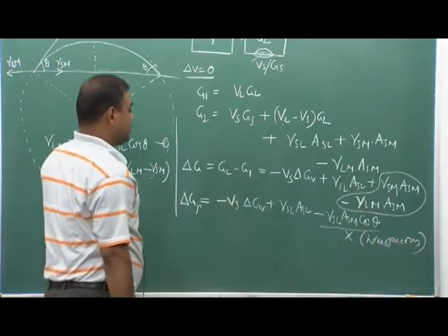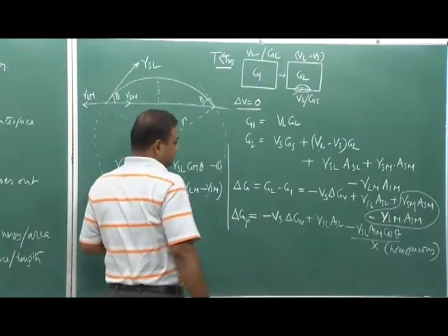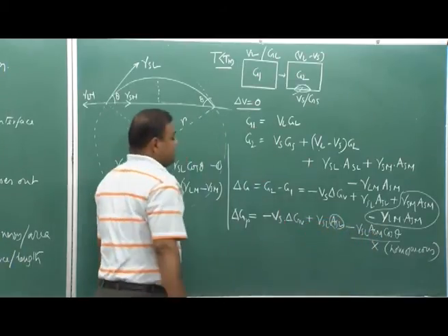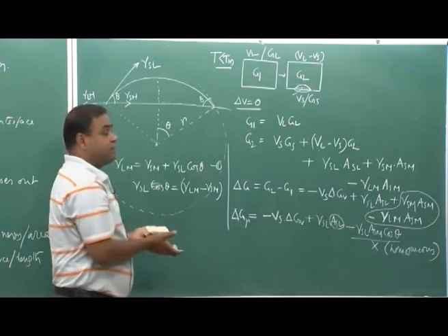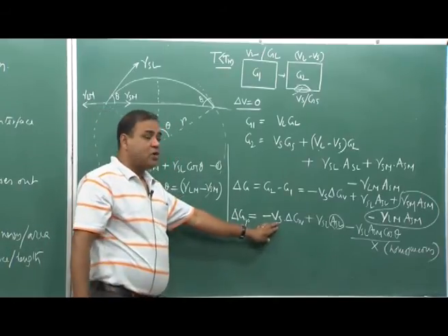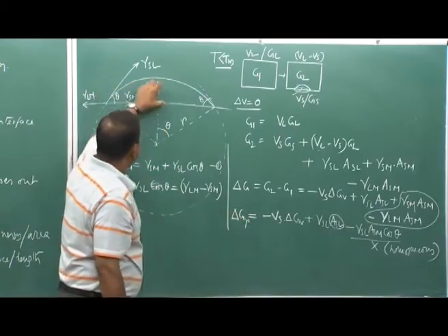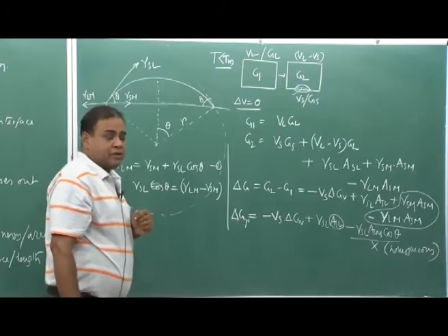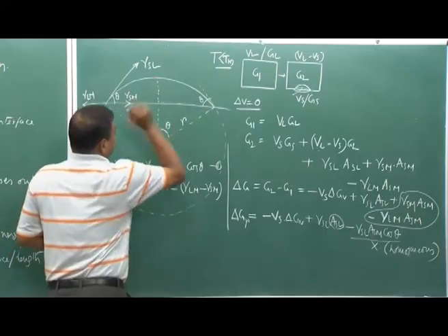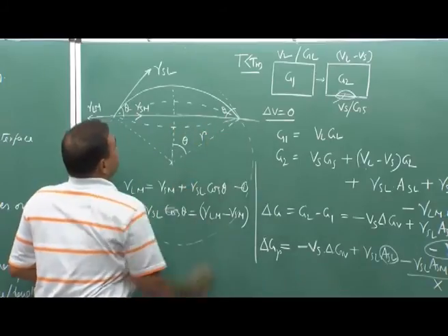Homogeneous nucleation, it was not there, but in case of heterogeneous nucleation, that means when we have a mold surface where the solid is forming. So, we have this equation, but this particular area is also not the total surface area of a sphere, rather part of that surface area, and at the same time this Vs is not 4 by 3 pi r cube, rather this is the volume only of this particular portion, not the entire portion. So, the entire problem lies in the calculation of this volume and the surface area of this particular portion, particular region.